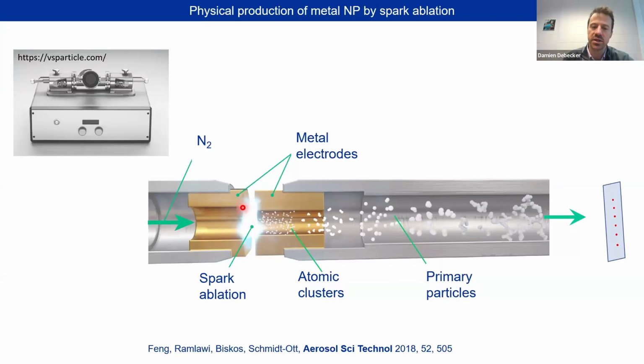The conditions here are extreme, but very, very locally, you have thousands of kelvins, so very high temperatures. And at those temperatures, a tiny amount of the metal will vaporize. This is called ablation, and you will form atomic clusters, which are swept away with a cold inert gas. We use nitrogen in our case, and then they will just agglomerate or aggregate and form what we call primary particles, or even bigger particles if we need.